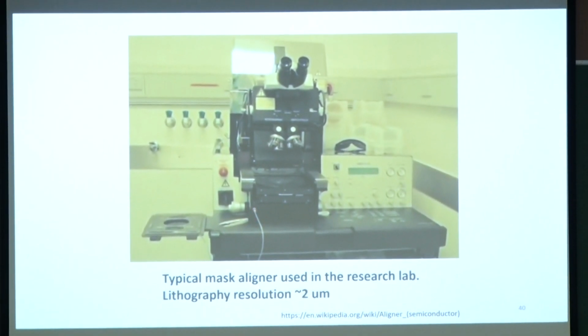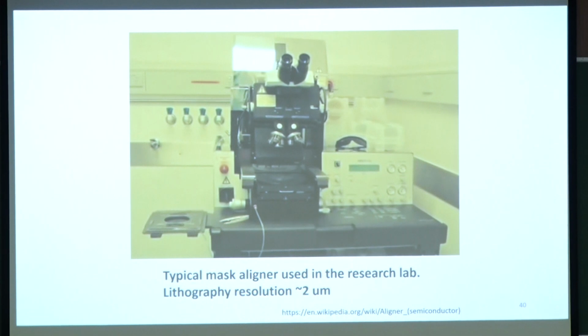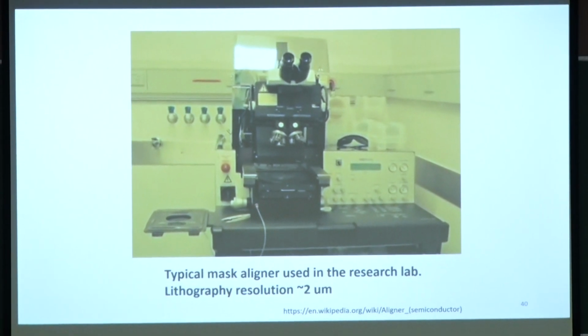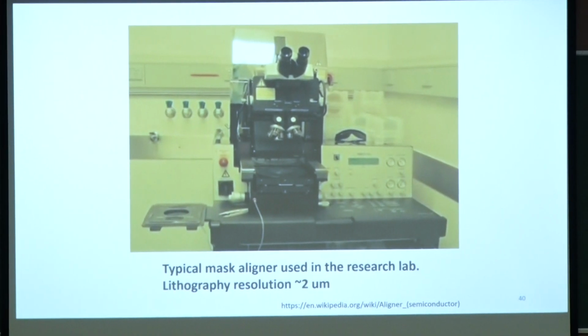This basically applies nitrogen pressure to do the hard contact, because to transfer the pattern nicely you do not want a gap between them. So, you apply pressure using the air, okay, and there is a particular value of pressure you should be applying. So, it is called hard contact, and that will give you the best result. So, if you want to get something like a resolution of 2 micron, you have to do it in the hard contact mode, but some kids who are not very aware about the system, they can break the mask, and mask is very costly. So, mostly people go with the soft contact. Okay.